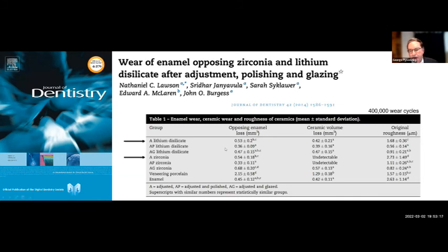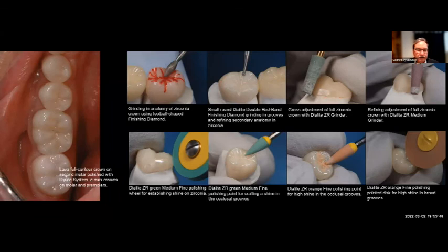And then the ideal would be polish and glazing, but sometimes from a laboratory perspective, it's quicker to just put a glaze on it. And so the glaze you saw is about 0.47. On zirconia, same situation, adjusted, very rough. If we polished it, we cut it down in half. And actually in glazing, because the glaze wore off here and it was unpolished underneath, we achieved a higher wear pattern on that overall. So again, adjusting and polishing is very critical to the success of these final restorations.